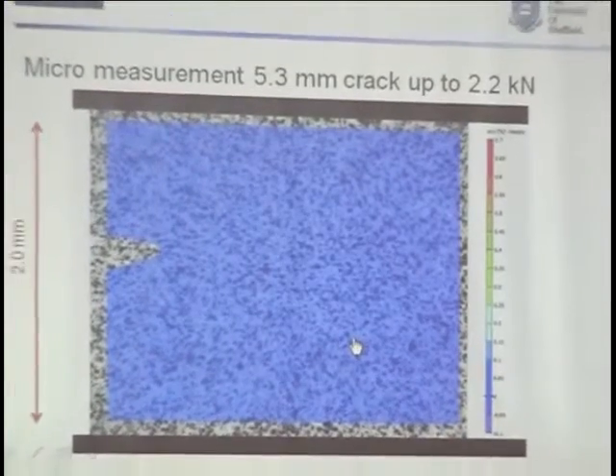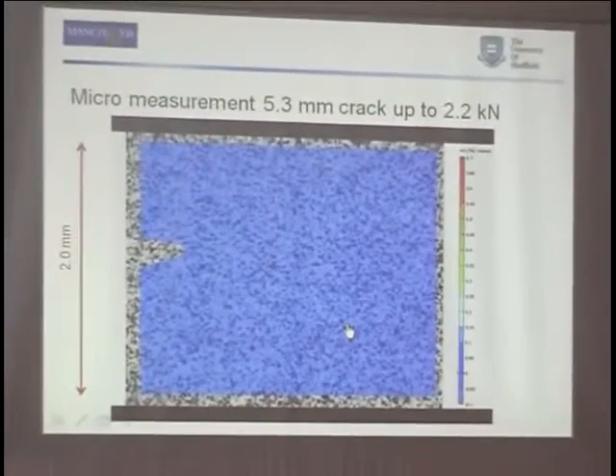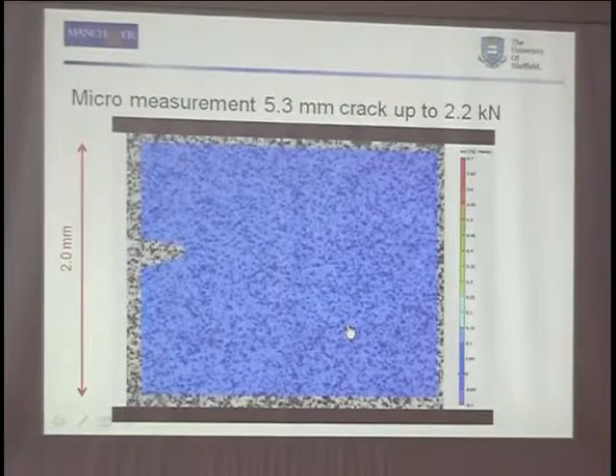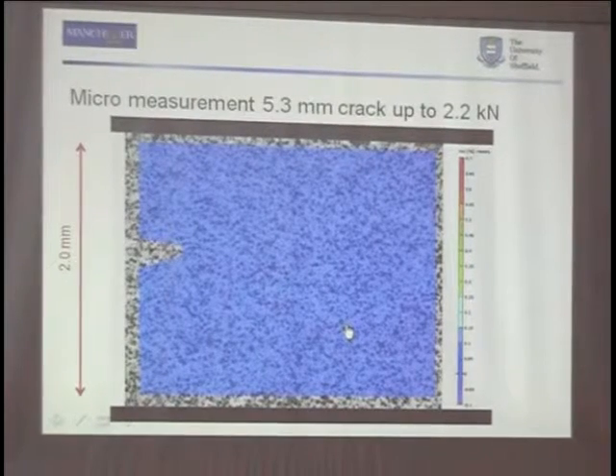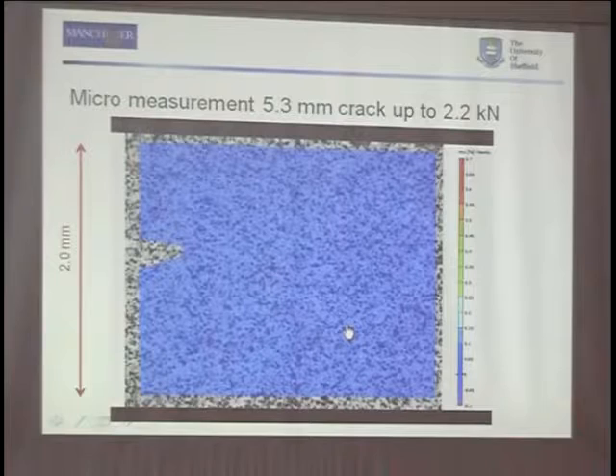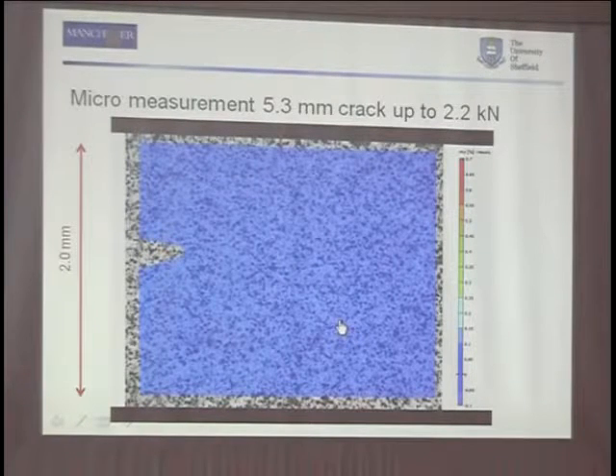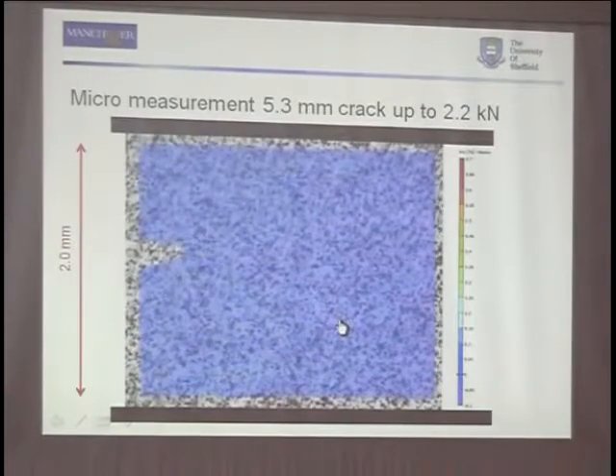On the reverse side, this is the cyclic data that we obtained. As you can imagine, on the macro side, we didn't really see very high strain. The strains were in the region of 0.2%. So in the far field ones, you only get the elastic part and not the plastic. But from the microscope data, you can see the plasticity around the crack.